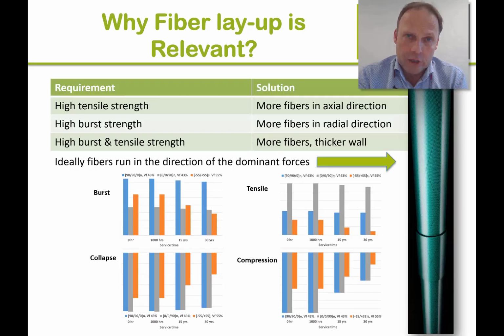So one of the things we have to think about is the fiber layup. The fiber layup is the term in composite country for the orientation of the fibers. For instance, if the requirement is very high tensile strength, then we put more fibers in the axial direction of the tubular. The other way, if we require high burst strength, then we will position more fibers in the radial direction of the composite structure. And if we want both high burst and high tensile strength, we'll just have to apply more fibers in both directions, which results in a thicker wall of the pipe.